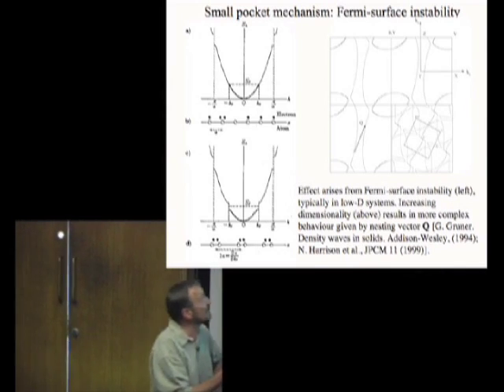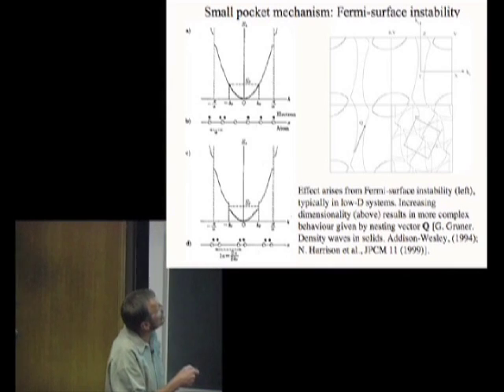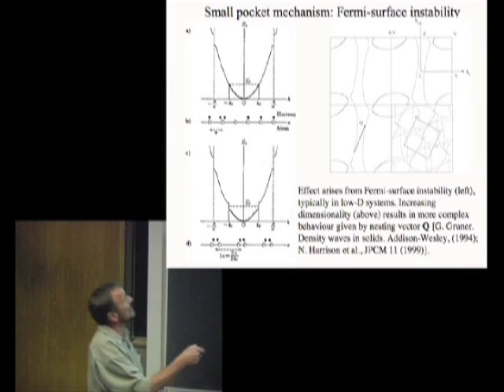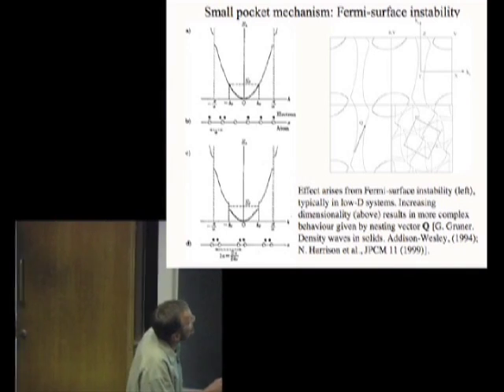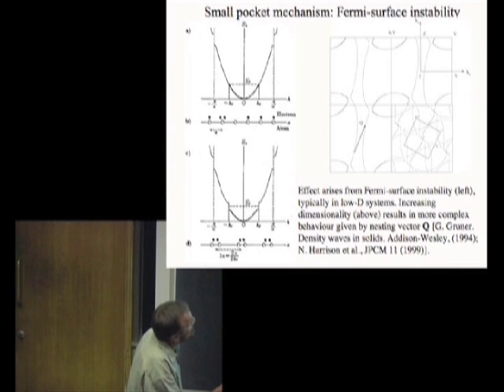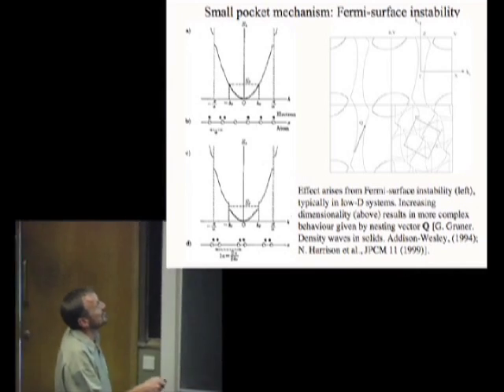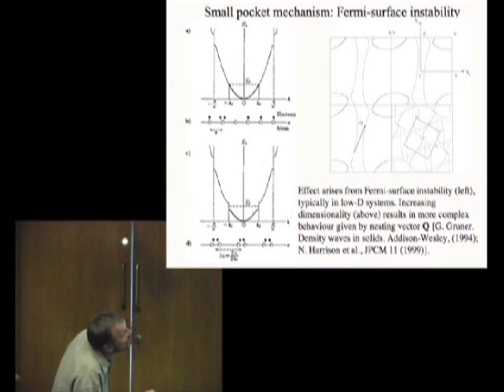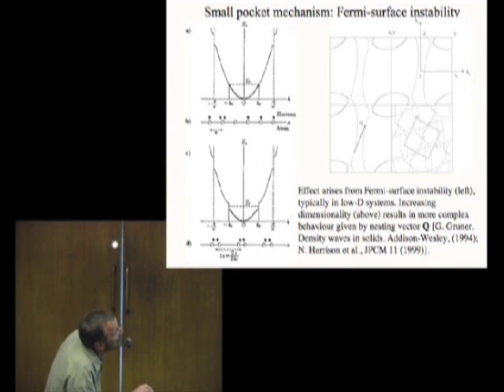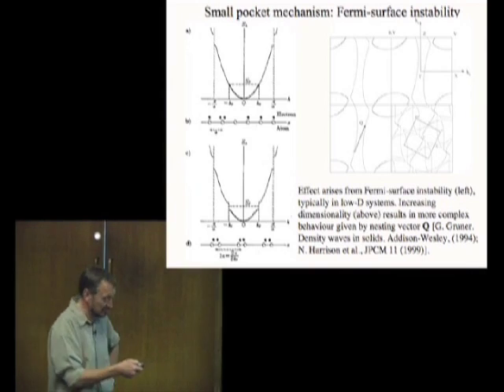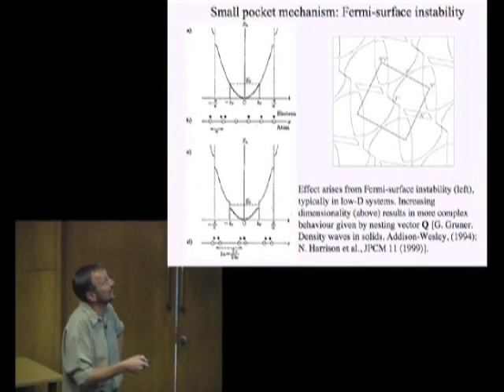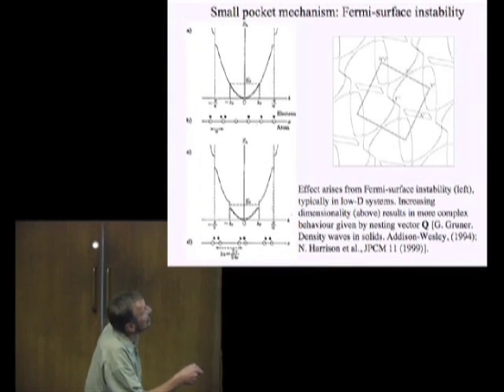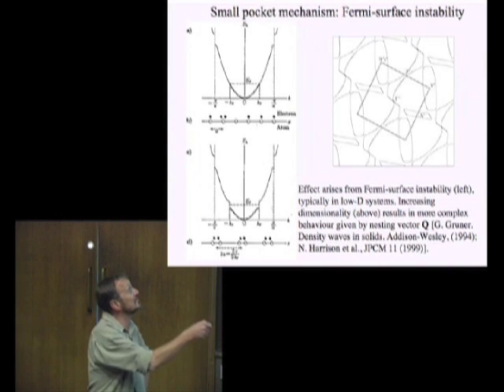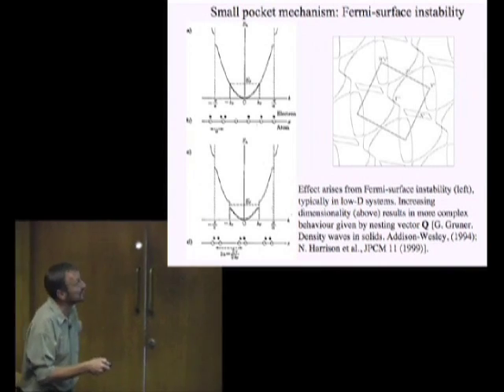But you've introduced a new periodicity into K-space. That means that if you take anything that's remaining in K-space, it has to be mapped all over K-space by this periodicity. So we take this thing here and we map it all over K-space, and it gives us a right mess of a Fermi surface. But you can see that the general principle is that if you have one of these distortions, it tends to give you smaller sections of Fermi surface than the original ones you started with. This is a blow-up of that region, and you can see that the original large piece of Fermi surface has been changed into all these little bits by one of these distortions.